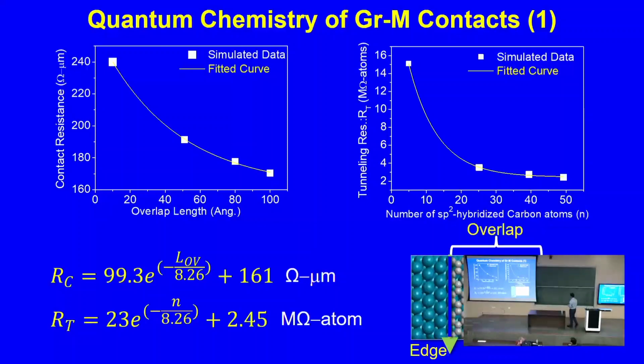So we dug deeper into that, and what we found, when we started looking into the orbitals, and whether the orbitals have changed in the overlap region versus the edge region, and if there is any hybridized state formed, is that in the overlap region there was no bond formation. It was all van der Waals force of attraction, and it was a tunneling contact, or Schottky contact.